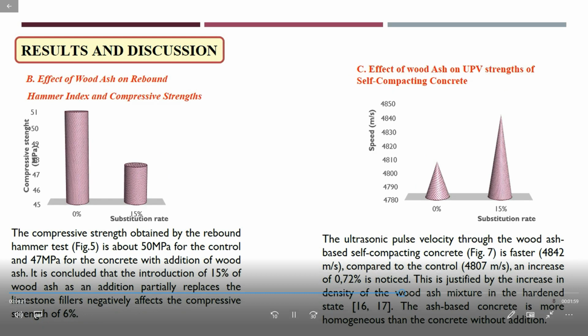The compressive strength obtained by the rebound hammer test is about 50 for the control and 47 for the concrete with addition of wood ash. It is concluded that the introduction of 15% of wood ash as an addition partially replacing the limestone filler negatively affects the compressive strength. The effect of wood ash on ultrasonic pulse velocity of self-compacting concrete: the ultrasonic pulse velocity through the wood ash-based self-compacting concrete is faster compared to the control. This is justified by the increase in density of the wood ash mixture.